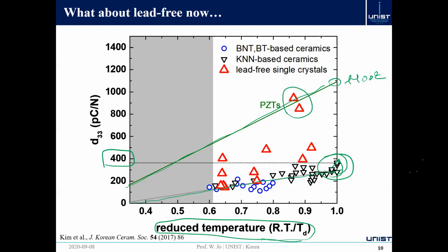And the single crystal, of course, gives you really wonderful properties, as you can see here, but a single crystal is not really cost effective. It's really expensive. That's the first. And then a single crystal is highly fragile. That's another problem for real-time applications. So I also did another survey of the literature and found that texture is another way to overcome these limitations.